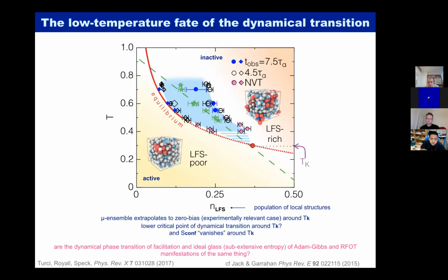It's actually a very interesting phase diagram. To be honest, to me it's very surprising, because you are using a kind of glass mu ensemble. If you think about a normal thermodynamic system, it's not very common for any system to have two critical temperatures. But most of them have some reasoning. You have some competition, then you have two critical points. Now in this phase diagram, if it is true, what is the underlying physics to drive the system to have two critical points?